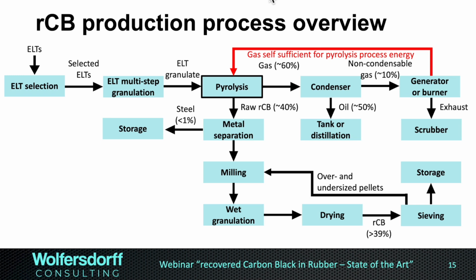Plus also, the condenser is key because it tells the sulfur where to go. If the sulfur goes in the gas, we have a low sulfur oil, which means the oil is a very high value oil. And if the sulfur goes in the oil, then of course the oil pricing is a little bit more inferior. Typically, if you have 10% gas, we're talking about self-sufficiency, meaning that we can heat the pyrolysis kiln with the pyrolysis gas. And then to be clean, if we burn the gas, we also have to go into the scrubber to take out any sulfur components from the gas combustion.